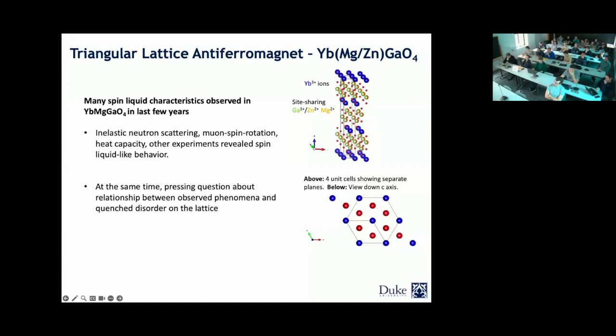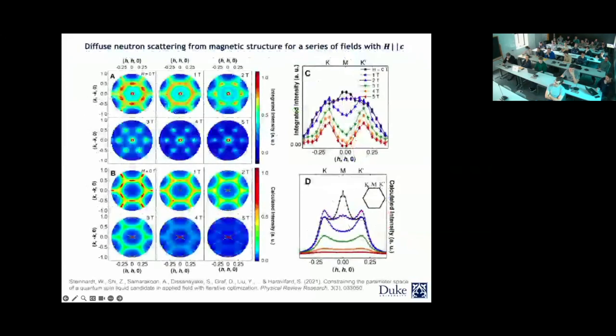By the time that I started to pay attention to this system, most of the ambient condition measurements were done. So we were able to synthesize the material. We also observed that there's chemical disorder. However, what was lacking was a field dependence, or using a magnetic field as a tool to understand the physical phenomena a little bit better.